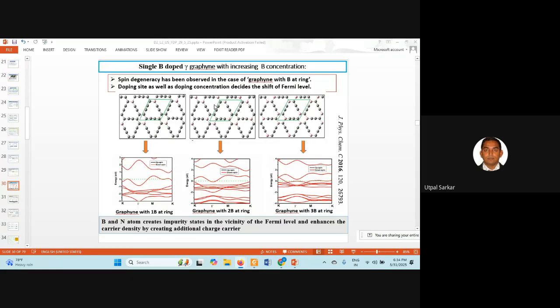These are the corresponding band structures for boron doping. Okay, so here for single boron doping, you see the asymmetry of the band structures here. So you see some of the bands are crossing the Fermi level here. This is the Fermi level, and this is for one boron, this is two boron, this is three boron. Okay, so these are basically crossing the Fermi level. Okay, and it is not located at the gamma and M points. You see. So here boron and nitrogen create impurity states in the vicinity of the Fermi level and enhance the carrier density by creating additional charge carriers. You see here. Okay.